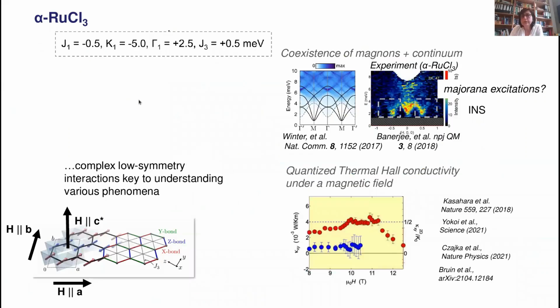Nevertheless, even though the system orders - and these are the values of the interactions we have for these materials, on the order of milli-electron volts - even though it's not purely Kitaev and it orders, if one looks at the spectrum, here in inelastic neutron scattering, the spectrum of excitations is rather anomalous. At low temperature in the ordered phase, one would identify this as your magnon excitation of the zigzag order.